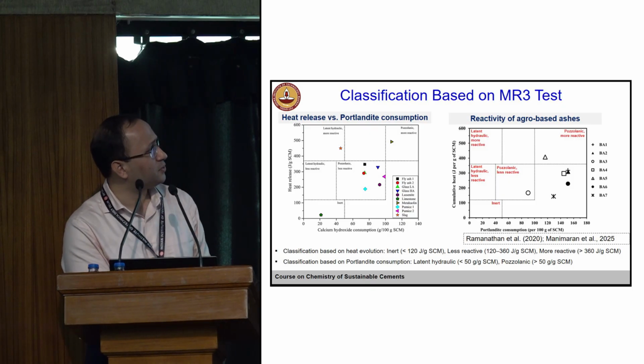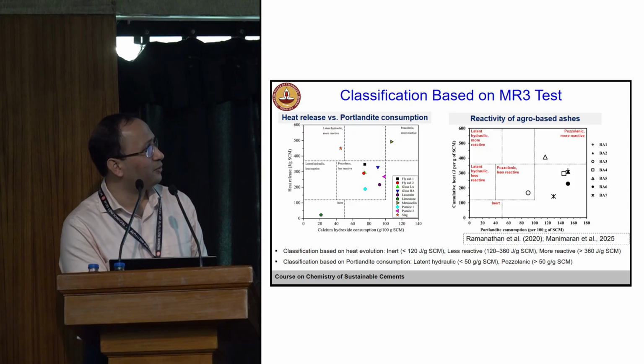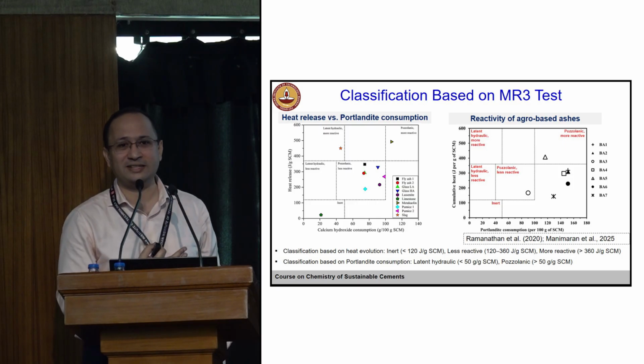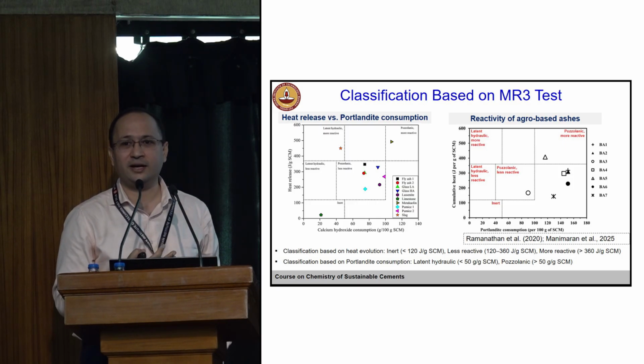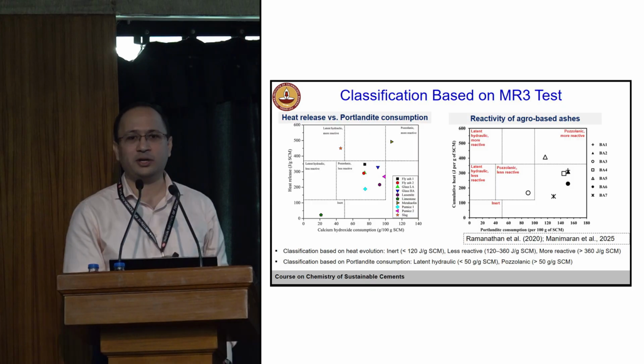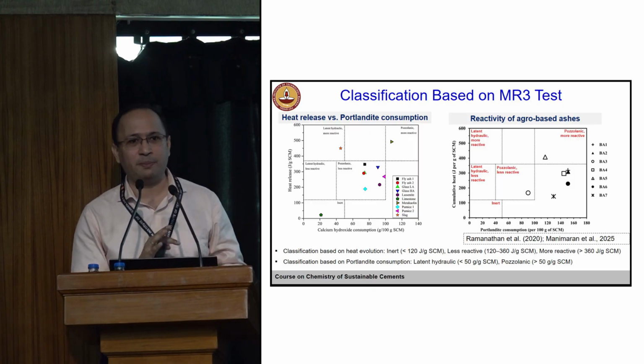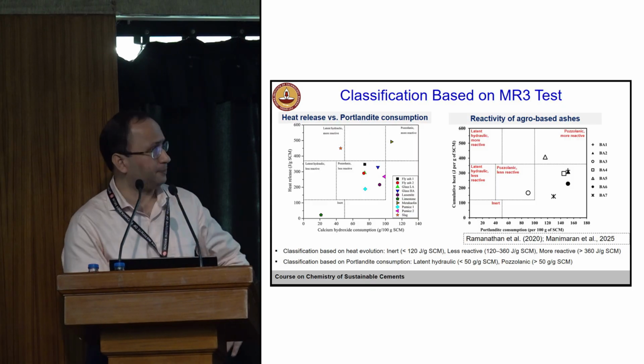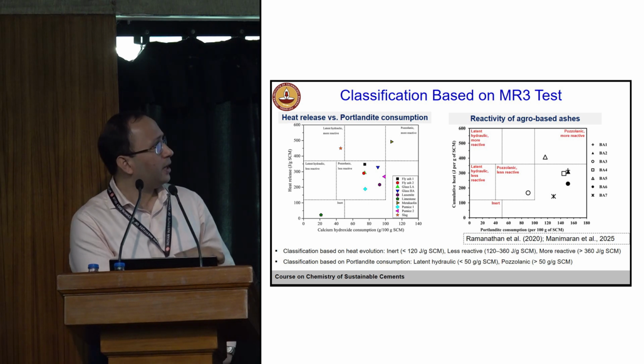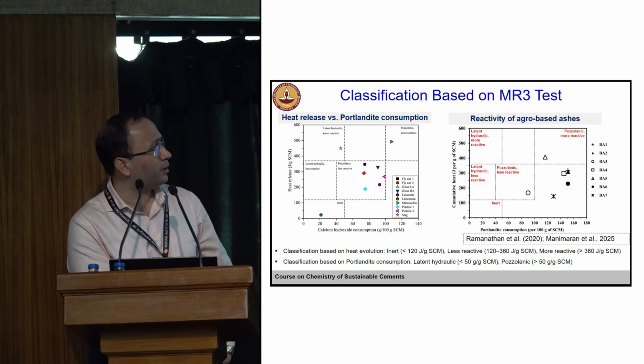And this was the study done by Neela, where we looked at different types of biomass ashes. If you follow, let's say in India, we have a lot of biomass ashes, right? Depending again on the source, whether it is rice husk or sugarcane bagasse, whether it is mixed with petroleum coke, your composition will change. It may have alumina. So again, this can be classified into whether it is pozzolanic less reactive, pozzolanic more reactive.